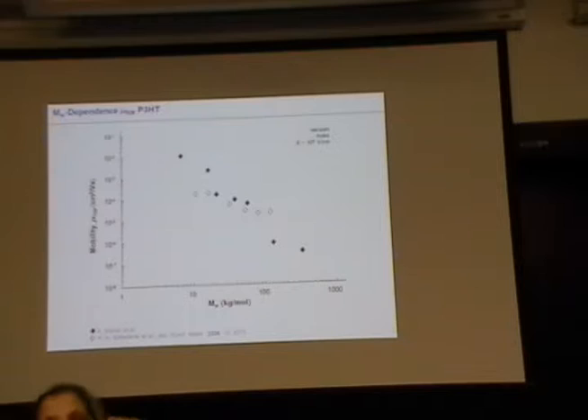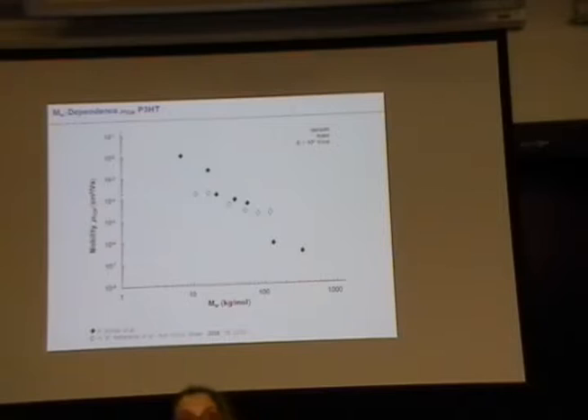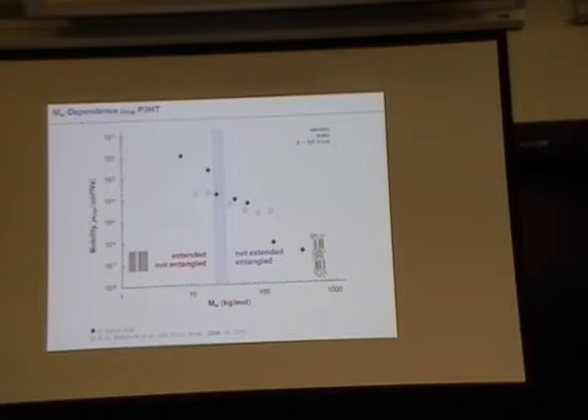There's a bit of salt in the whole theory when we do time of flight. We have a diode device — two electrodes, we shine light on it, create charges, apply voltage, and measure the time. We see the opposite trend. This implies either time of flight is not so dependent on film forming, or that the bulk mobility much more depends on the degree of crystallinity. We still have to look into why bulk charge transport doesn't really depend on extended versus non-extended crystals and more looks like dependence on crystallinity.